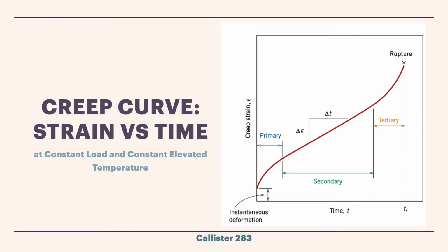This graph depicts the behavior of creep on metals. There are three main phases in this deformation. It starts with an elastic instantaneous deformation when some constant load is given, shown as the immediate jump on the y-axis. The first phase is called the primary creep, also called transient. The characteristic of this stage is its decreasing slope as time goes by. Physically, it shows that the material does not deform easily.